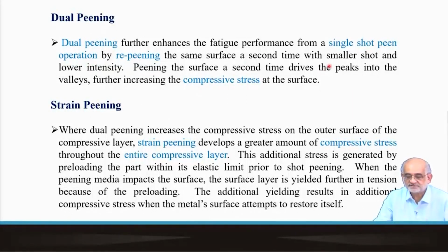Dual peening is when you repeat the same shot peening operation with slightly smaller diameter pins or smaller diameter spherical objects, and with lower intensity, so that you simply add on. You have already created residual compressive stress up to a certain region, say the depth is about 0.2 millimeter, but on the top 0.1 or 0.05 millimeter, you can create even deeper, larger residual compressive stress by repeating with the dual peening operation, the second peening operation.